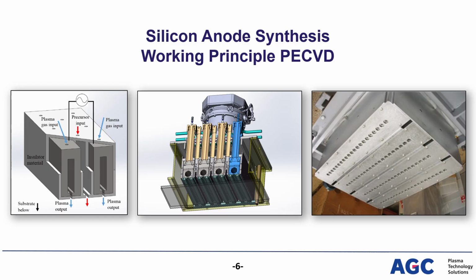The electrodes have the form of an elongated cavity with multiple gas inputs and an arrangement of gas outputs facing towards the substrate. The process gas, argon in this case, is fed into the electrode cavity and is ionized by applying an alternating current or a pulse DC power with a frequency in the range of 20 to 100 kHz. The ionized process gases will then uniformly exit into the process chamber through a series of holes.